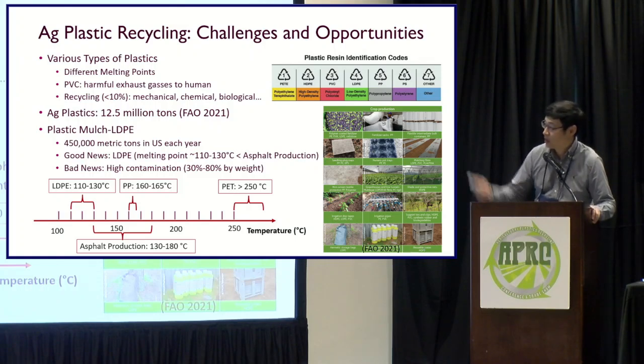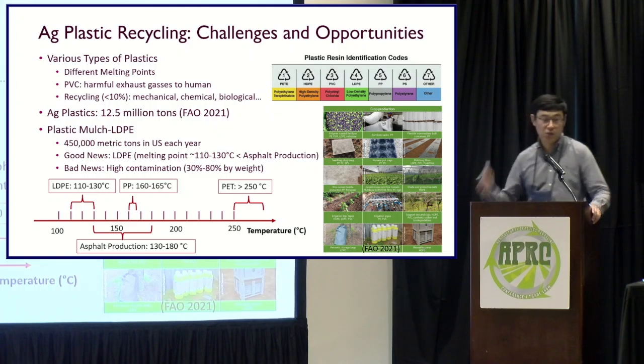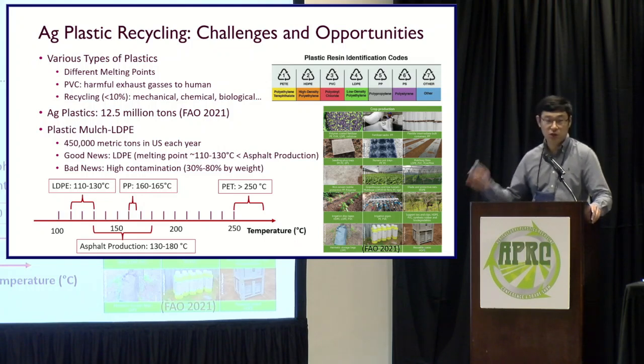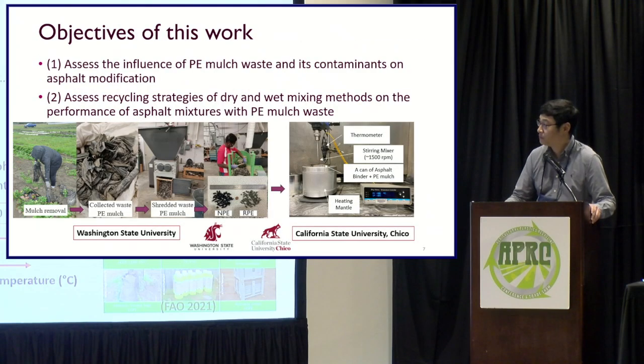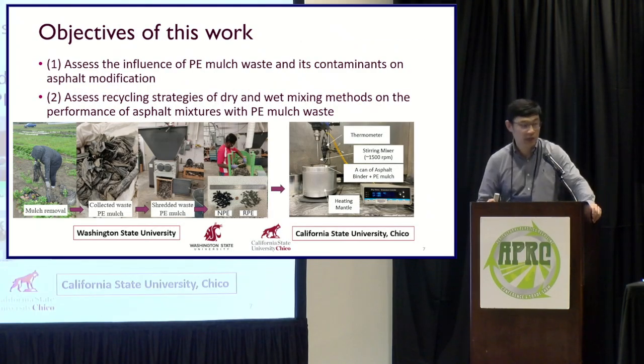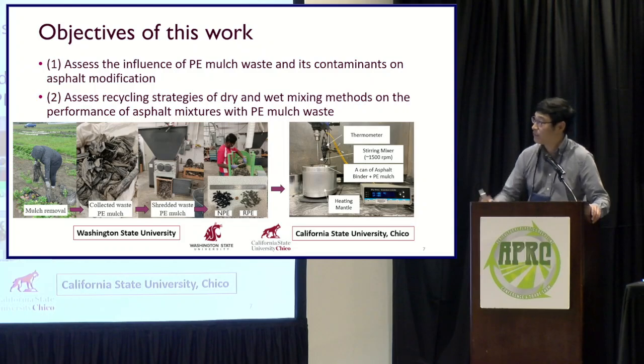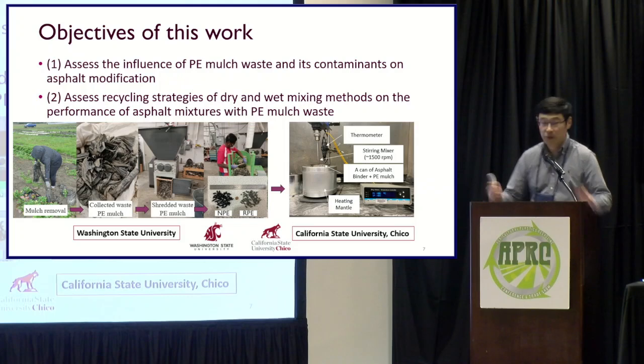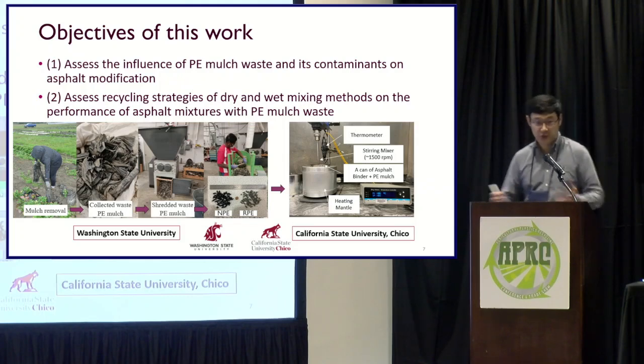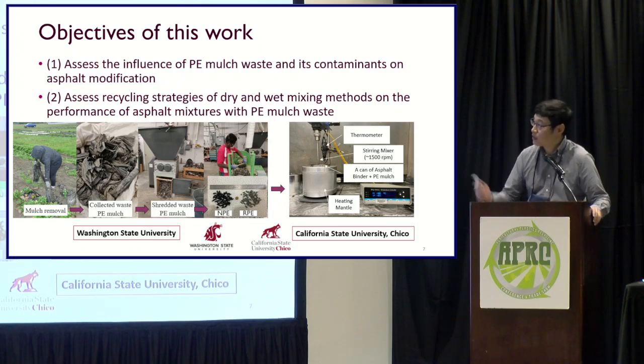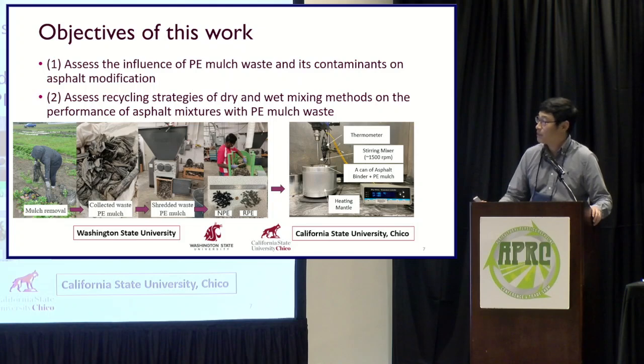However, it has a higher contamination level, 30% to 80% by weight. So in this project, we are going to answer this question: how will this highly contaminated LDPE mulch affect the performance of the asphalt? Well, we have two objectives for this work. The first one is to assess the influence of the PE mulch waste as well as its contaminant on the asphalt modification. So we will compare the modification effectiveness between the new PE mulch and the recycled PE mulch. And also assess the recycling strategy by using the dry and wet mixing method on the performance of the asphalt mixture with the PE mulch waste.